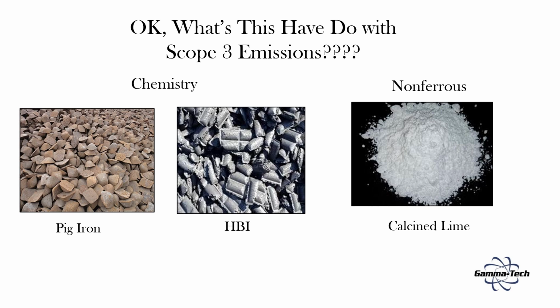Now let's talk about how we as a steel industry have been dealing with this problem. Again, visual inspection is ineffective at determining the copper level of shredded scrap coming into the mill, so that increased copper level and increased variability that have transferred into our steelmaking process, we've dealt with by diluting the problem at the furnaces. Being able to put pig iron, HBI, DRI, ore-based products into the furnace reduces the final copper content in the steel bath and keeps us in specification. The other key factor here is that when you're allowing copper contamination to be a part of that ferrous scrap stream, you're allowing other contaminants in there as well, both non-metallic and non-ferrous. We've had to account for that in our slag balance by adding a higher percentage of burnt or calcined lime into the charge to keep those acids as they come into the process in check and keep our slag chemistry correct.